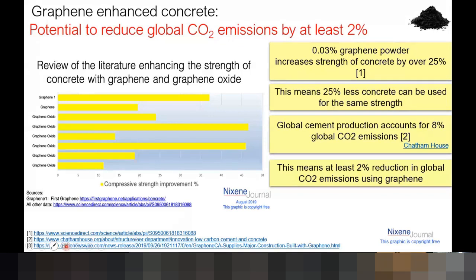Yeah, and also with it, there's a decrease in porosity. When they were originally going to build, it was for a seawall, and they were so amazed by the properties, even the flow and cure properties, that they decided to build everything with it. And again, from the UK, we need the UK government to get involved and drive certification and testing to drive this out globally. Yeah, and the porosity was important, Mike, because you don't want salt water penetrating the concrete and corroding the rebars inside the concrete. Graphene stops that.